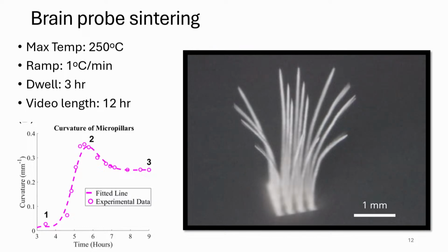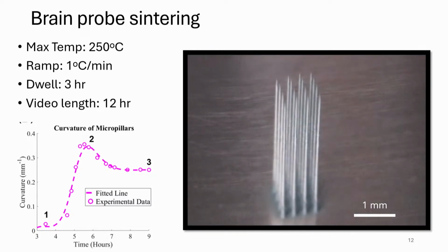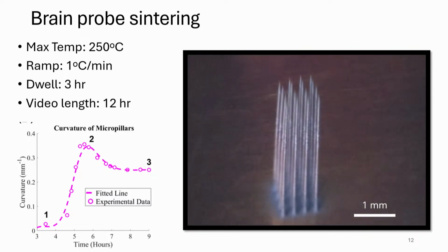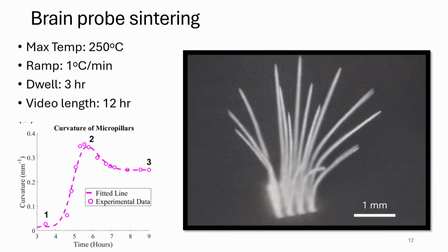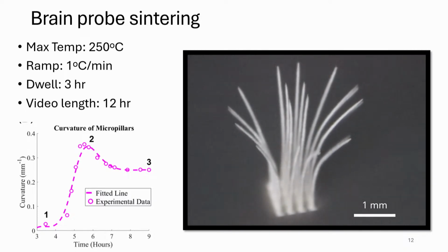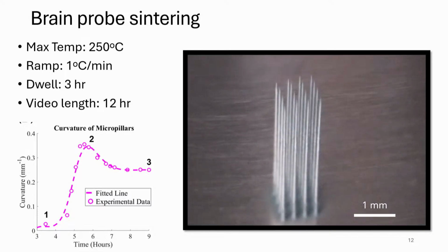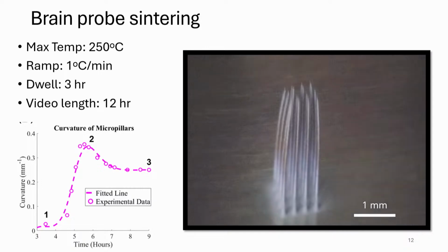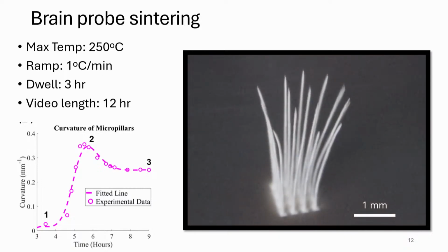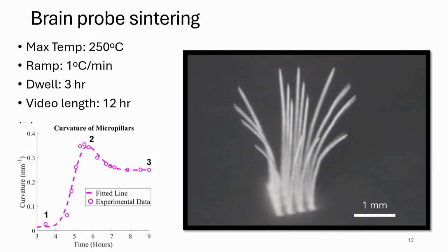they're embedded into gooey polymer ink, right? So they're printed with a print head to form needles which are about 20 to 50 microns thick and several millimeters long.